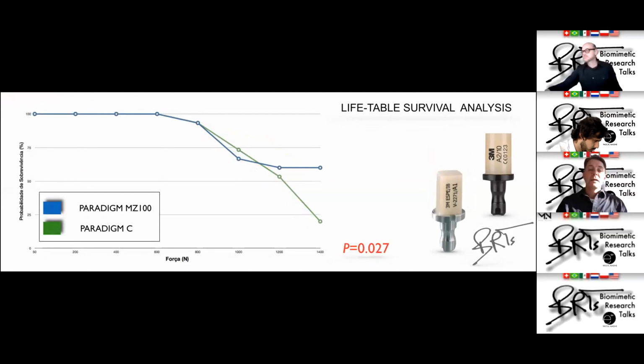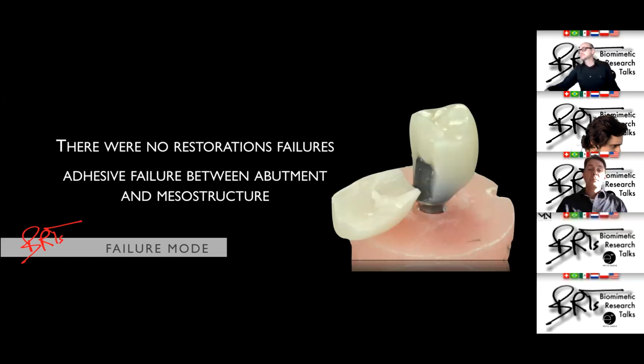But when we compare the materials, composite resin and ceramic on the hybrid abutment, the composite resin went better. It's the same behavior as in the previous experiment with ceramic abutments. The composite resin appears to work better, or to make the difference, at high loads, as you can see. The failure mode was different in this experiment because there were no restoration failures. It was an adhesive failure between the restoration and the structure.